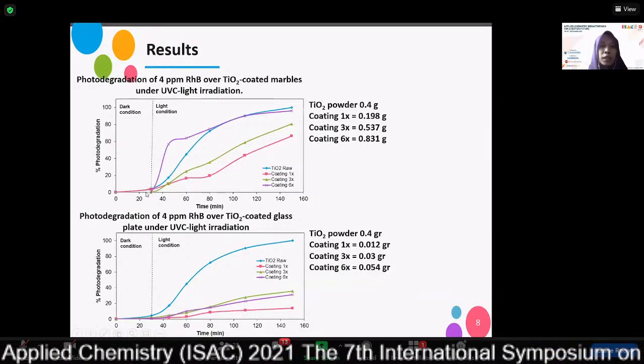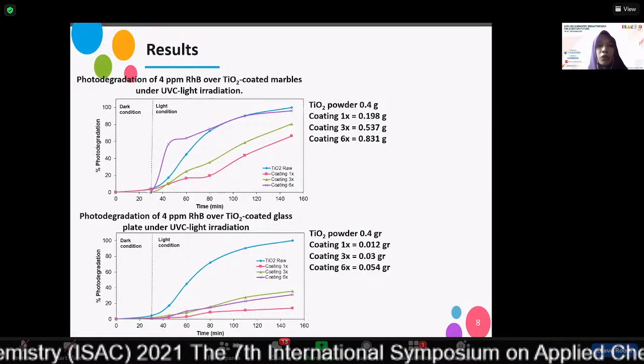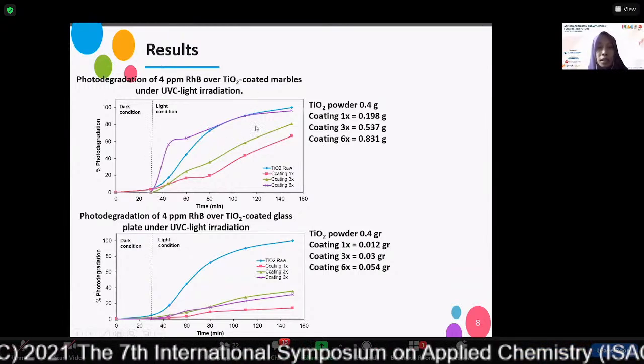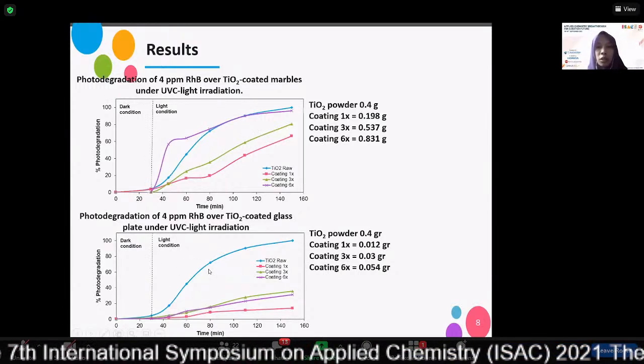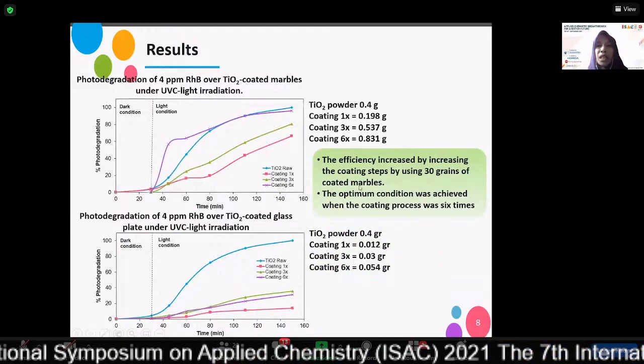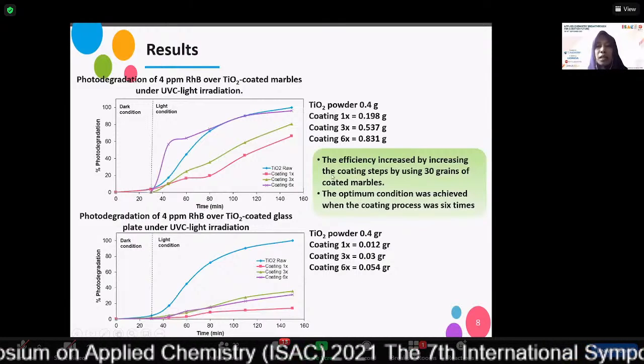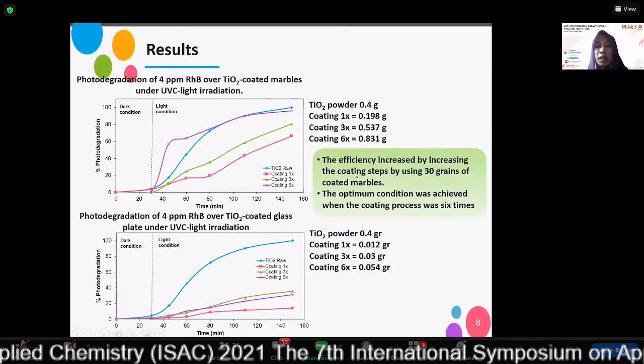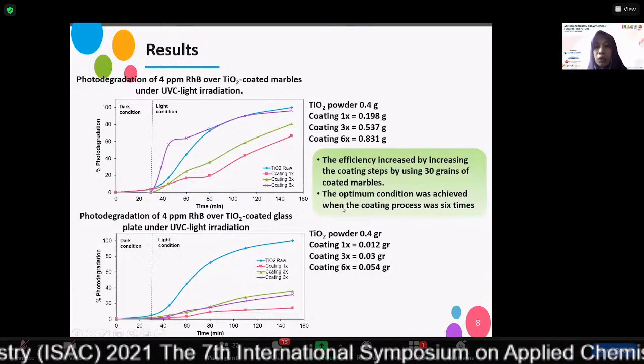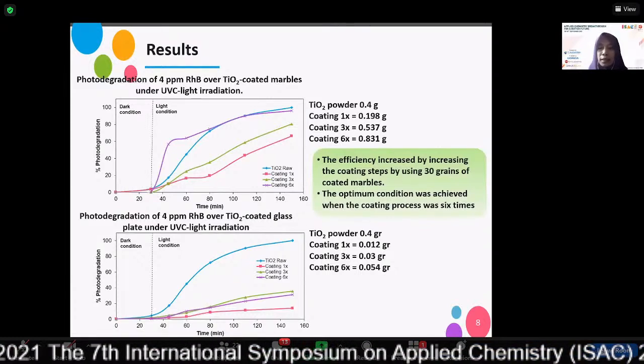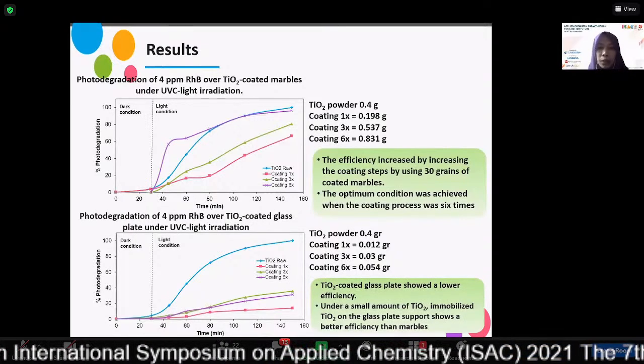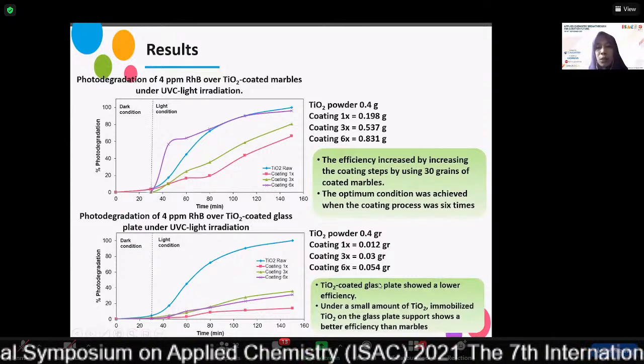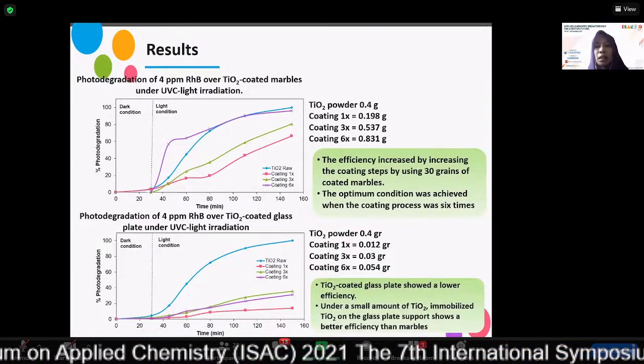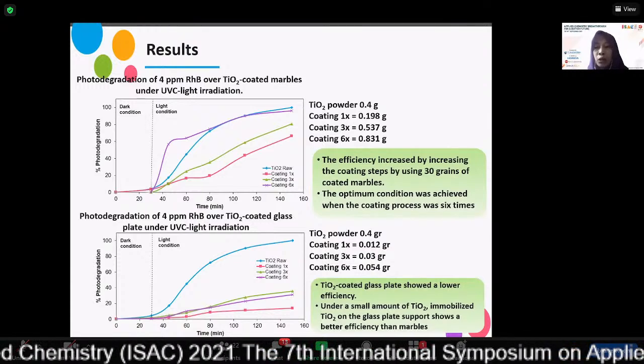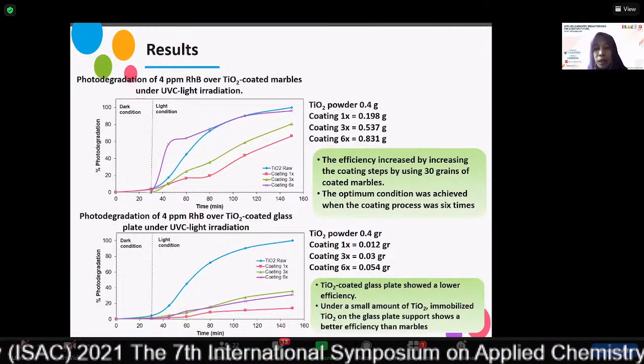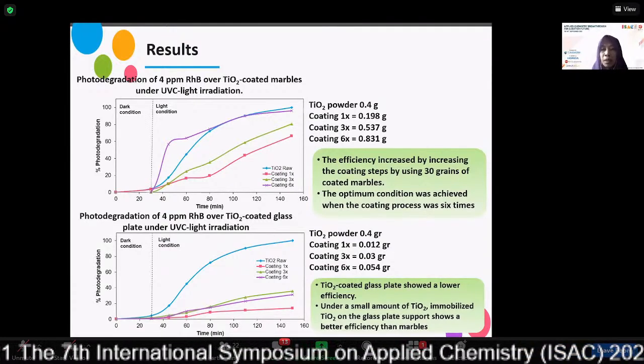This is the result of photodegradation of 4 ppm rhodamine B over TiO2 coated. The first one is marbles, and the second one is on the glass. The efficiency increased by increasing the coating step by using 30 grains of coated marbles, and the optimum condition was achieved when the coating process was 6 times. And for the glass plate, TiO2 coated glass plate showed a lower efficiency. Under a small amount of immobilized TiO2, the glass plate support shows a better efficiency than marbles.